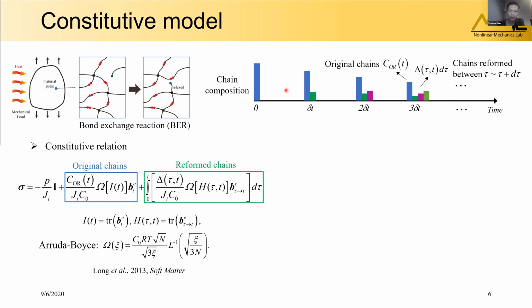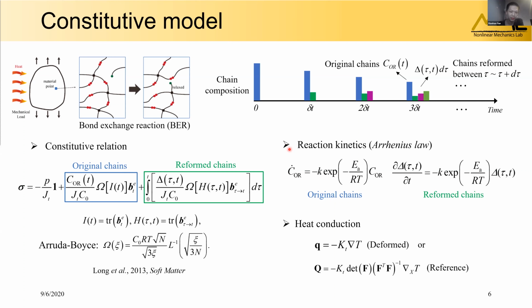The original chains experienced deformation from time zero to the current time t, and the reformed chains born at time tau will experience the deformation from tau to t. So we can sum up the stress of different chain groups and obtain this form for the Cauchy stress. And the evolution of the chain composition is governed by the reaction kinetics, that is the Arrhenius law.